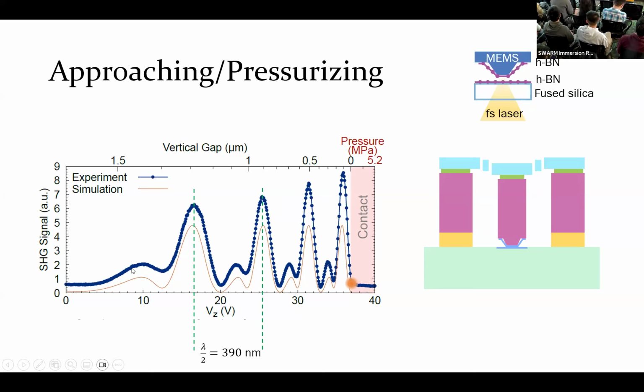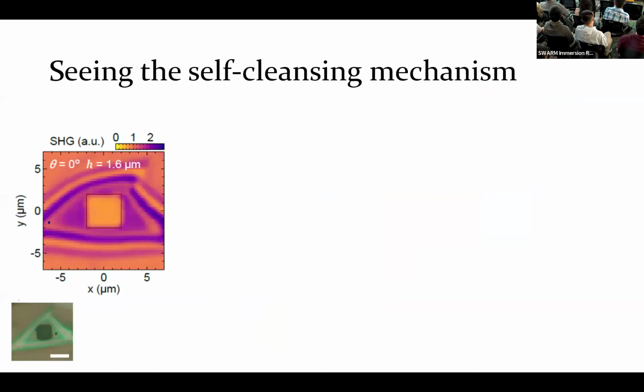And what you can see is that after these 4 oscillations, the signal settles to a constant value and doesn't change anymore with the voltage we apply onto the MEMS actuator. And that basically means that the 2 sheets of 2D materials are now in contact, so they cannot move anymore. So this is basically a sanity check that this device is working as expected, and we're getting a good interface between the two 2D materials.